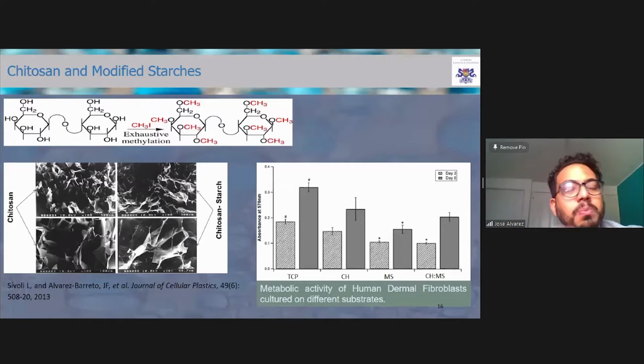But the problem with this technology was that in order to create these hydrogels, we had to use a cross-linking material that's called glutaraldehyde. And glutaraldehyde is highly toxic, and it was a huge problem for us to get rid of the glutaraldehyde. We did it, but it was a very complex process to get rid of unreacted glutaraldehyde.